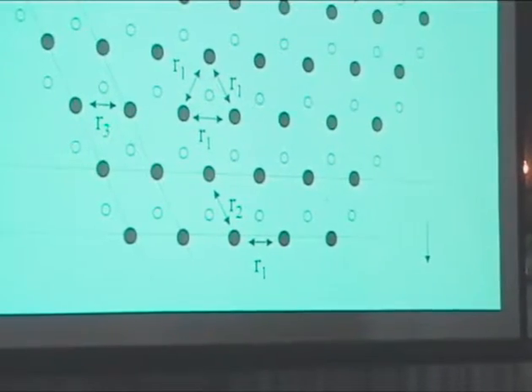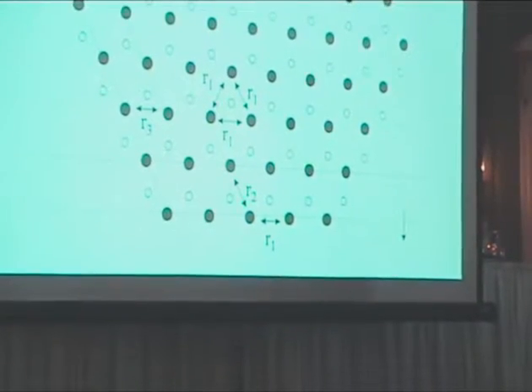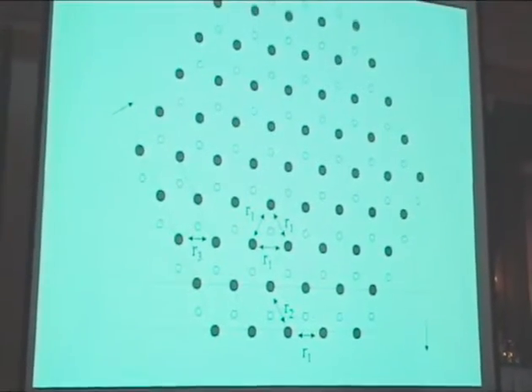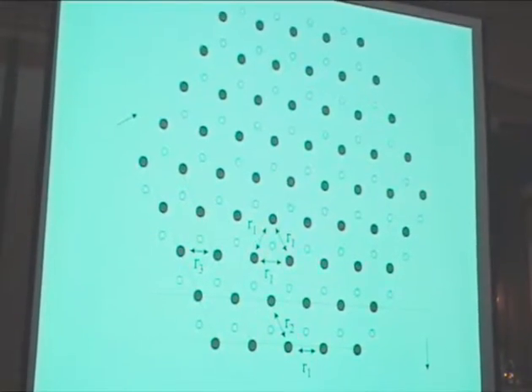So the idea came up that maybe the surface science is right, and so maybe at the edges of my crystallite of MoS2 there is a contraction, or there is a different position than in the middle. So when I got a postdoc for a couple of years, I suggested to him, let's try and simulate it by Monte Carlo methods. There are other methods, I'll show you one in a few minutes, but let's first go to this one, because I like this one, because for a chemist it makes sense to start from that side. You start with your chemical intuition, and then you try to come up with answers. Our chemical intuition told us that the inside is different from the outside.